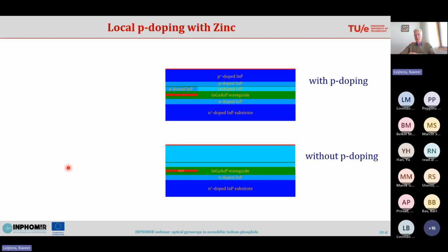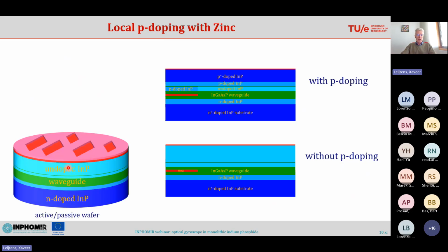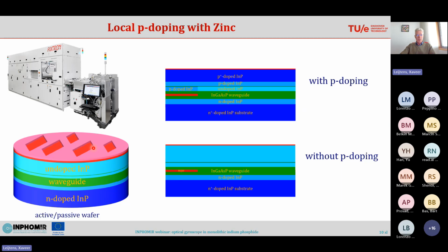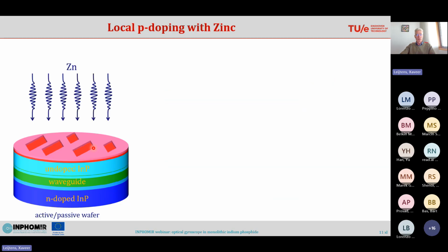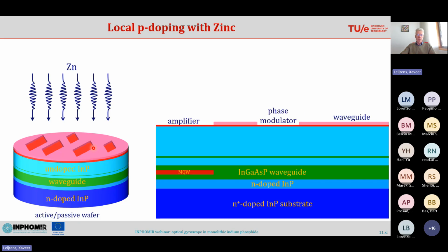Now what we do is we grow essentially the same layer stack, but without the p-doping. And then we have the wafer, and on top of the wafer we put a mask, and the holes in the mask are there where we have the amplifier, and also where we will have the phase modulator. Then this is put back in the reactor again, and with this reactor we will drive zinc through the openings in the mask only at those locations where it's needed. So the amplifier and the phase modulator need a PIN junction, and that's where we drive the zinc through this mask. So the zinc will be going in there, and that will provide the p-doped contacts for the modulators and the amplifier.